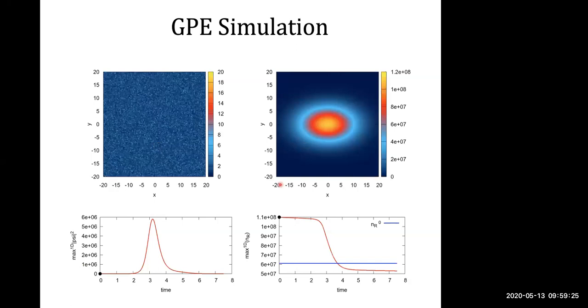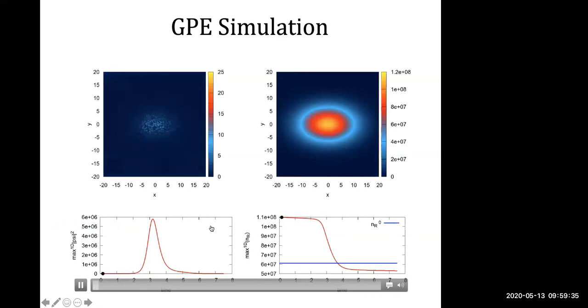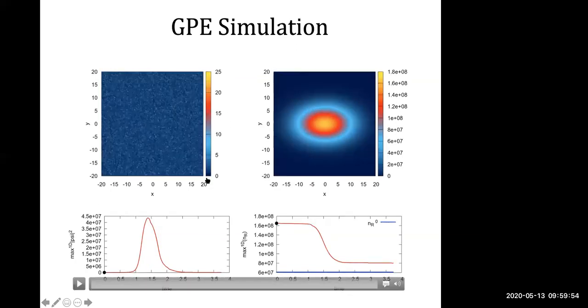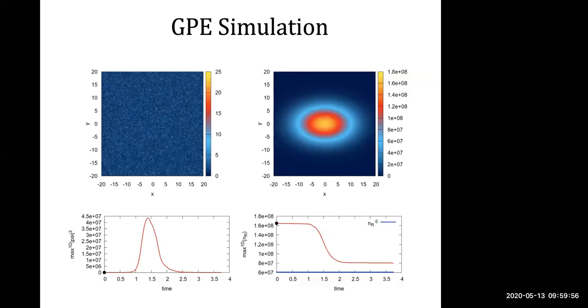Here we come in with an impulsive pump. This is the reservoir exciton density. This is the polariton density evolving as a function of time. These excitons are scattering into polaritonic states, and you form this nice stable condensate when you have a small pump spot. Now, if you increase either the pump power or the size of the pump spot, you enter a regime where these instabilities play a role.